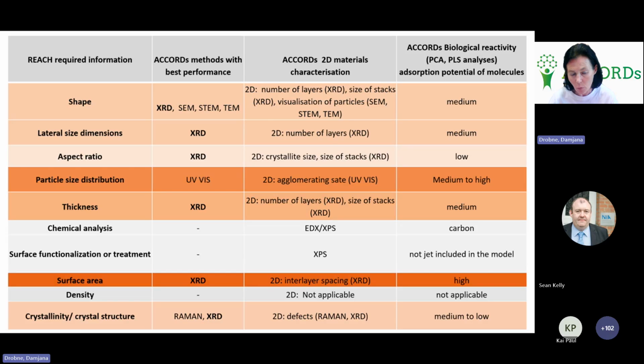If we look at this table, what we can see is that when we take into consideration all the characteristics that are included in REACH required information, we can see here a list of methods that could best address them. Of course, XRD, electron microscopy, UV-Vis, and also Raman are those that could best be used and are applicable for this purpose. Then we also see that in case of 2D materials, we can somehow translate or adopt these characteristics also to 2D materials. This is for sure not the final shape or naming. It's a matter of discussion among our project and also among the EU dealing with regulation, so we can adopt this, but for sure this could also be used for 2D materials.